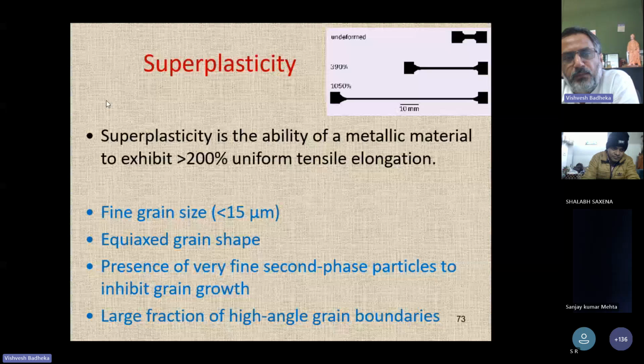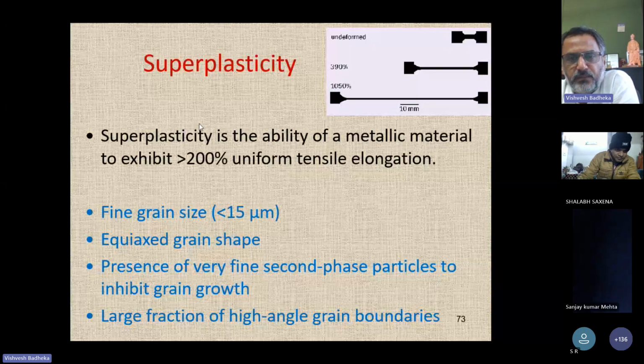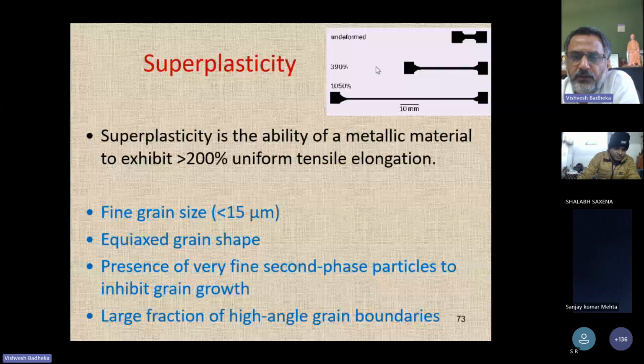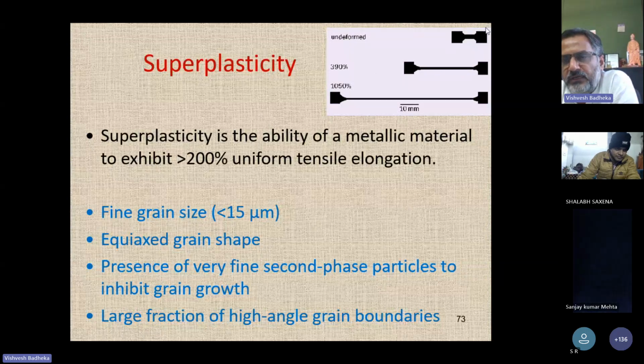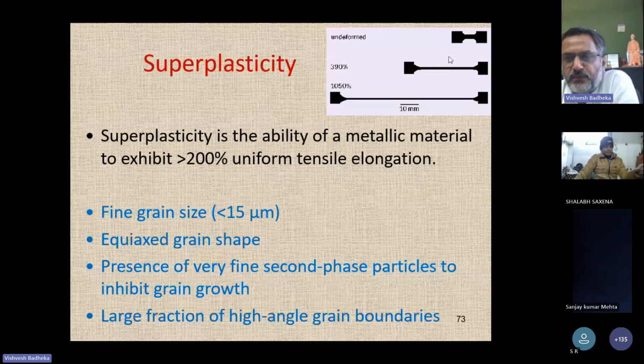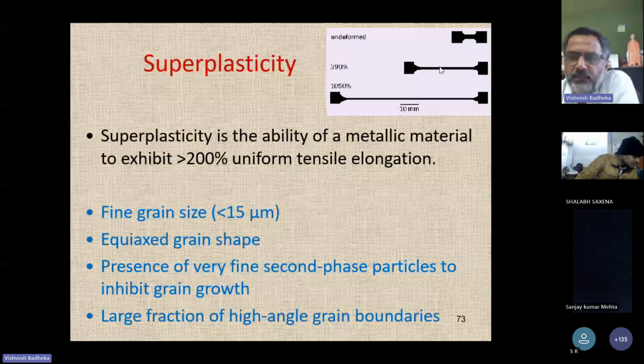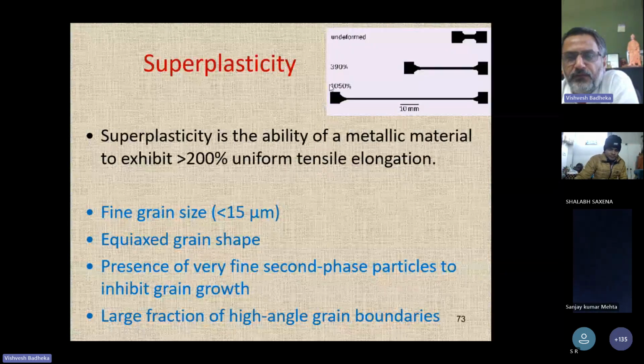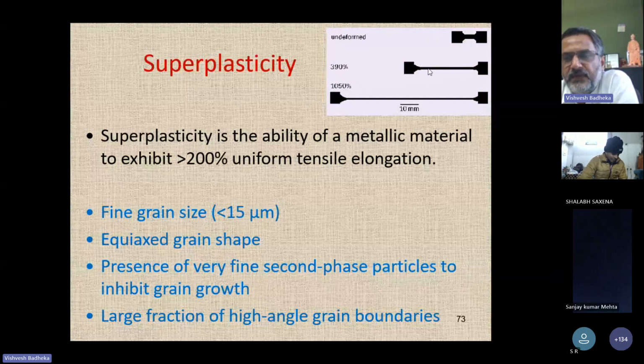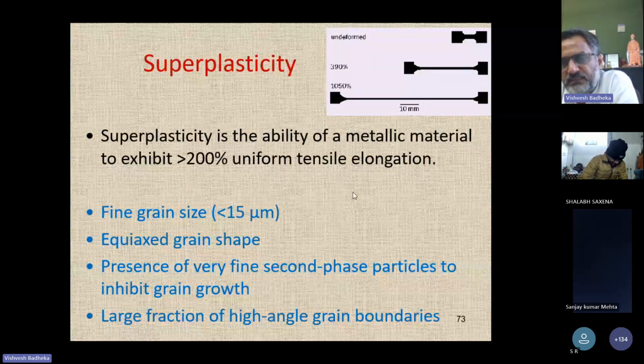So you take an aluminum plate and then you run it through a friction stir processing tool. So the grain refinement will take place. Say, for example, to help you out with an elementary understanding, you see there is your normal tensile specimen. And then when you deform the specimen after friction stir processing, if your material displays this kind of elongation, or maybe this kind of elongation, you see 390, 1050, if the material displays this type of elongation, then you can say your material has superplasticity.